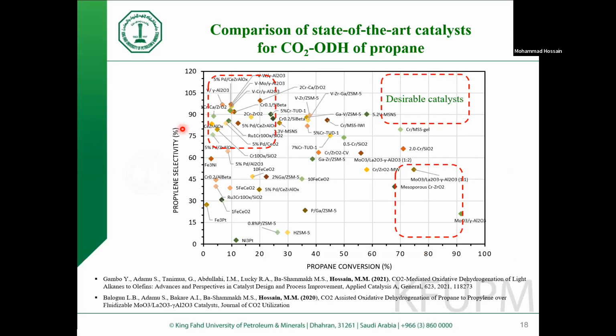Now we can compare different catalysts in terms of the conversion and selectivity. In this chart, we try to plot different catalysts from our group and from the literature, and it is clear that it is all over the map. When propane conversion is high, the selectivity drops, and most of the catalysts perform well in terms of selectivity at low conversion.